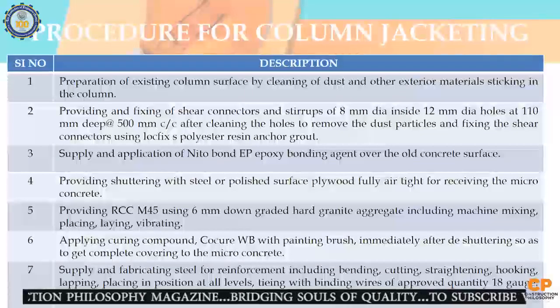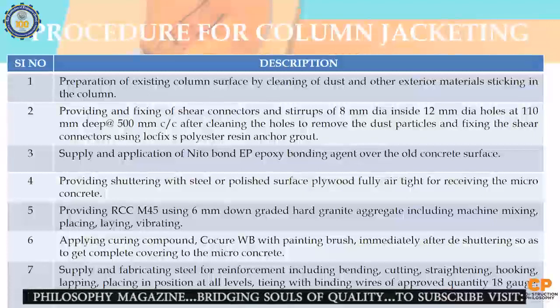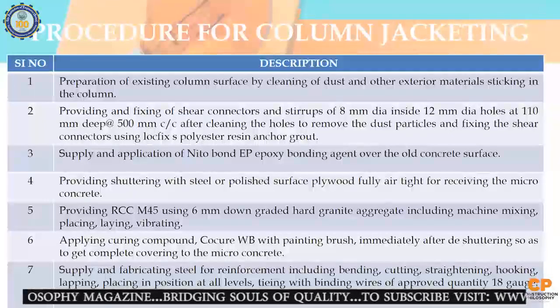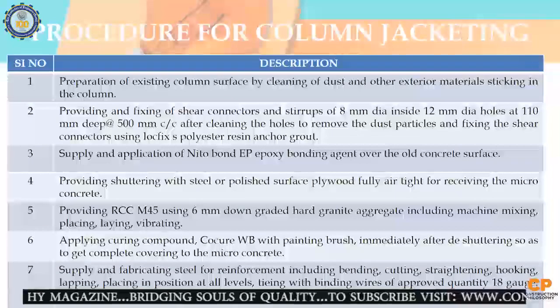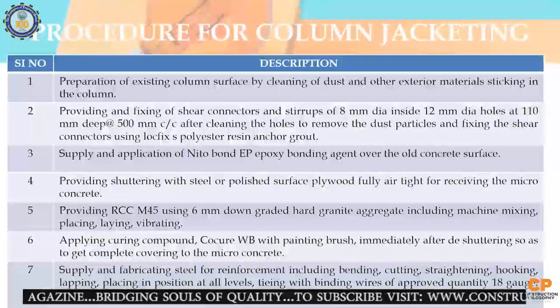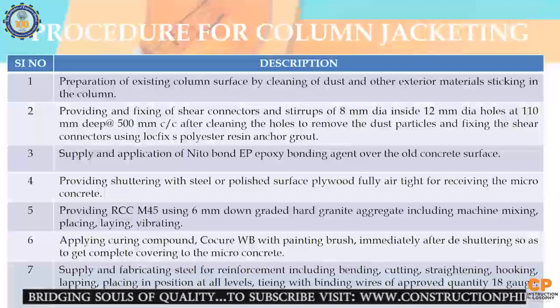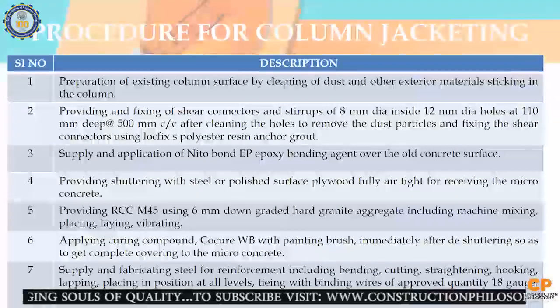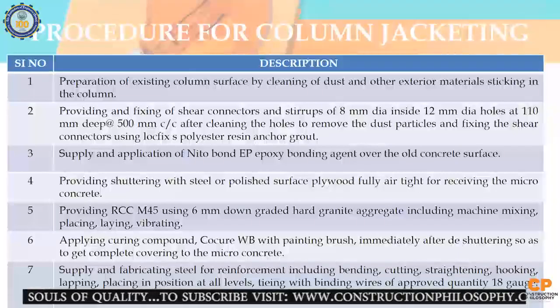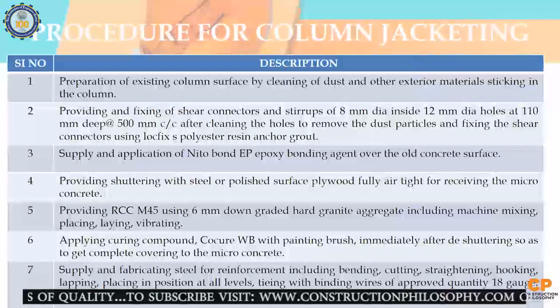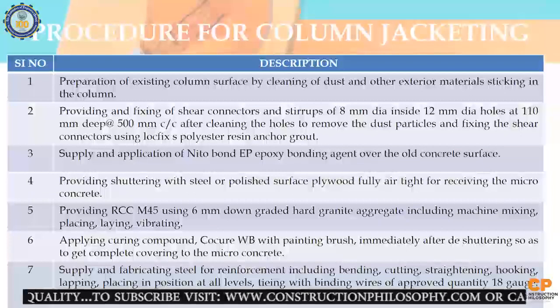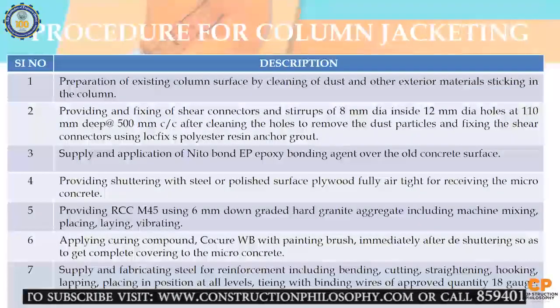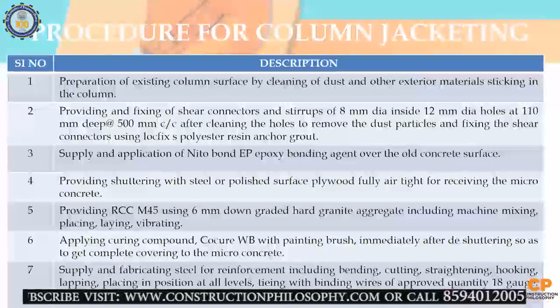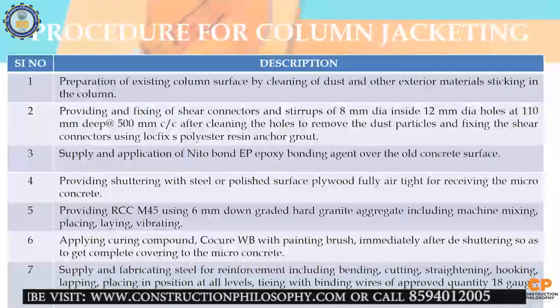Preparation of the existing column surface by cleaning dust and other material sticking to the column; providing and fixing shear connectors and stirrups of 8 mm dia inside 12 mm dia holes, 110 mm deep, at 500 mm center to center, after cleaning the holes to remove dust particles, and fixing the shear connector using Lokfix polyester resin anchor grout; supply and application of Nitobond EP epoxy bonding agent so that the old and new concrete get bonded with each other; providing shuttering with steel or polished surface; providing RCC M45 using 6 mm downgraded hard granite aggregate including machine mixing, placing, laying, vibrating, applying curing compound, and supplying and fabricating steel reinforcement.